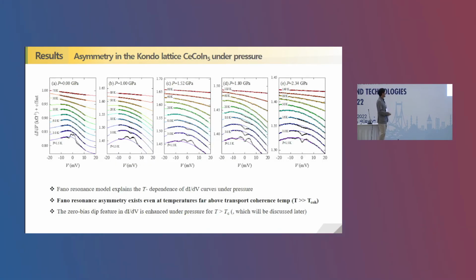So this is the data from 0 to 1, 1.52, 1.8, and 2.36 GPa, and those solid lines are the fittings. This very nice agreement suggests that the Fano resonance model in the Kondo lattice system explains the temperature dependence as well as the pressure dependence pretty well.